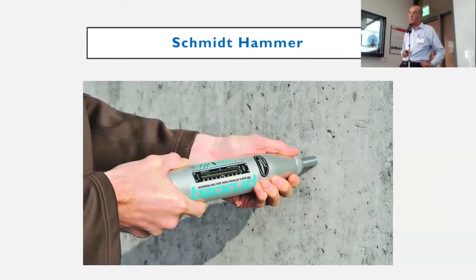That's a good question. It's very difficult to tell. The surface concrete that you're actually hitting with the Schmidt Hammer is measuring the strength of the cement paste in the concrete. Cement paste could or could not be the determining factor of the strength of the concrete. And as we know, compressive strength of concrete is really dependent on the water-cement ratio. So it's possible to have a really low water-cement ratio right at the surface, but inside, within the member itself, it is not that strong. And this is the problem with it. Whereas when you take a core, a 4-inch, 6-inch, whatever diameter core, and you bring it back to the lab, then you're testing the entire section.